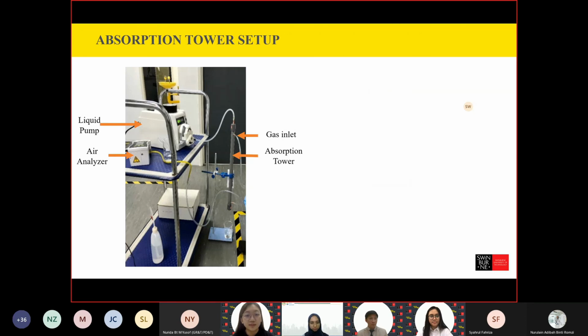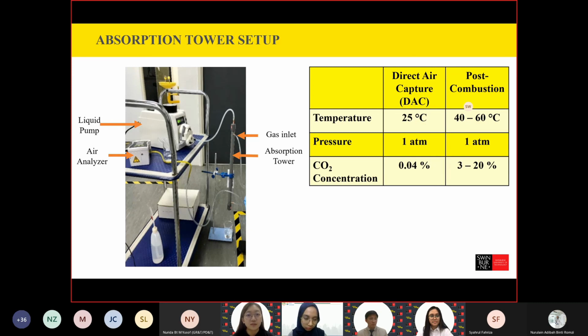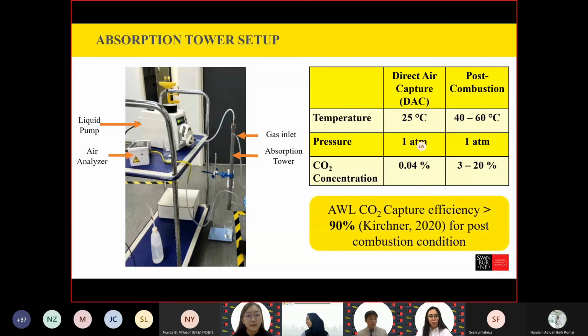This diagram shows the absorption tower setup. It uses calcium carbonate pellets as the packing, with compressed air and distilled water. In our project, ambient air with a CO2 concentration of 0.04% was used instead of flue gas CO2 concentration of around 3 to 20%. The operating condition hence is for direct air capture at 25 degrees Celsius and 1 atm. Future work is planned to utilize post-combustion CO2 concentration and condition. This work therefore is a proof of concept of the proposed idea at extremely low concentration. Reported AWL CO2 capture efficiency in the literature is greater than 90% using flue gas at post-combustion absorption condition.